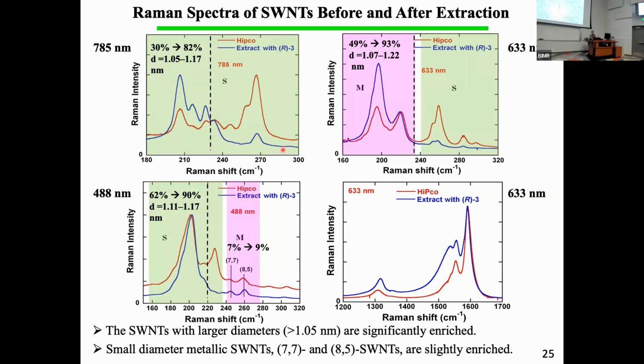This trace shows before extraction, and the blue trace shows after the extraction. You can see a very big difference between them. Before extraction, this HiPco tube includes a relatively larger amount of smaller diameter tubes, at least at this excitation wavelength. After extraction, the smaller diameter component shifts to the larger diameter component as a majority. At the 633 nanometer excitation wavelength, a similar phenomenon can also be found. Here the relatively smaller diameter shifts to the larger diameter.